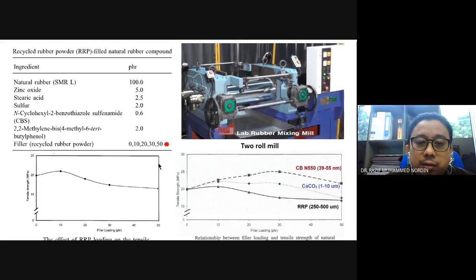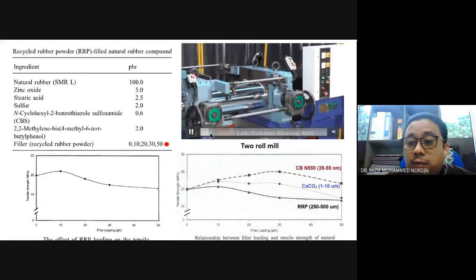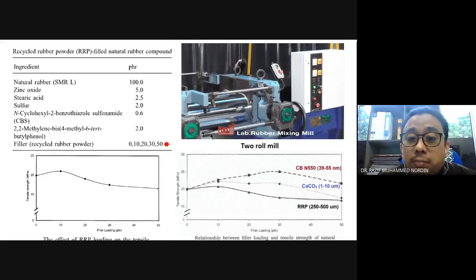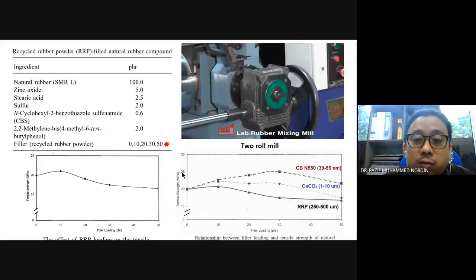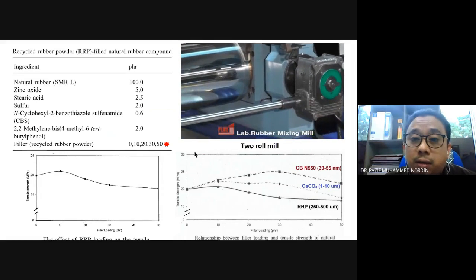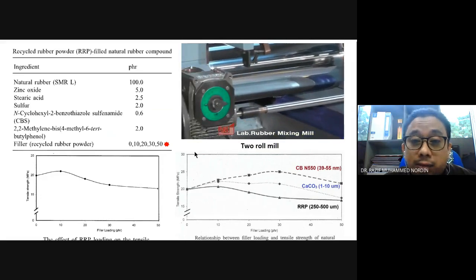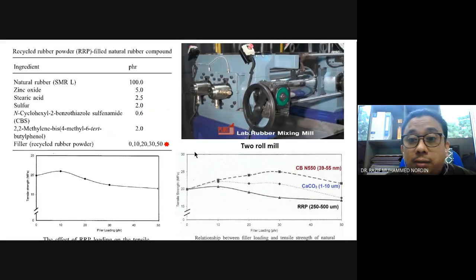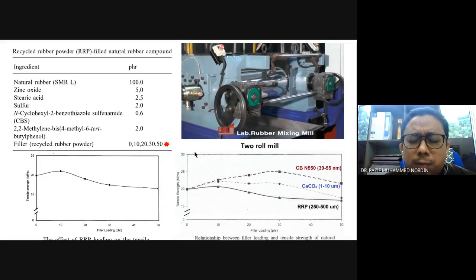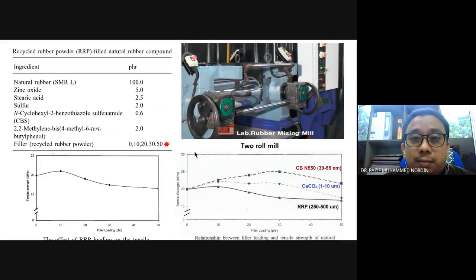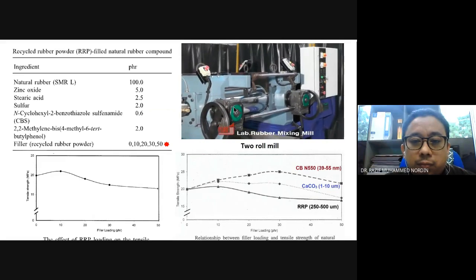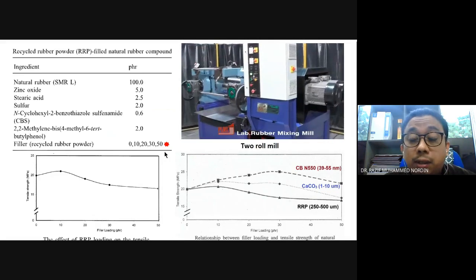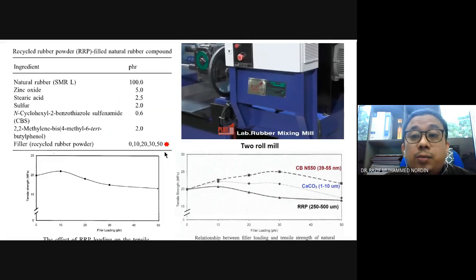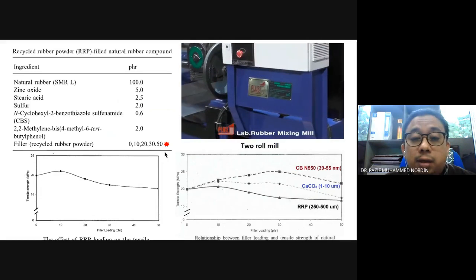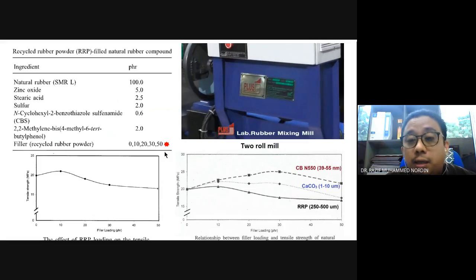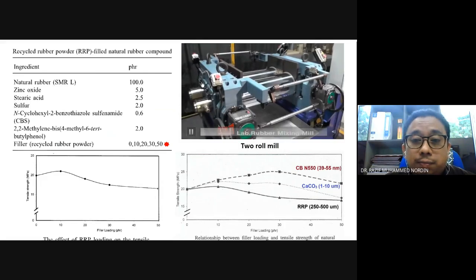It's very physically demanding if you process with a two-roll mill, but the good part is that you can produce 300 gram of sample per mixing within 35 minutes. Very fast. This 300 gram, you can use for a lot of testing. You can use it for thermal properties, mechanical properties, swelling, and typical characterization like FTIR, DSC, TGA, that is normal.